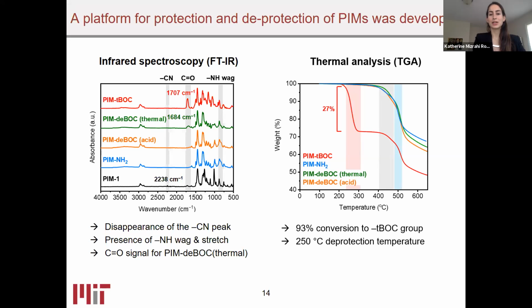In addition, we looked at thermal analysis to evaluate the deprotection temperature for the sample, which is about 250 degrees Celsius, as well as how much we were able to convert into the TBOC-functionalized sample. And it resulted in about 93% conversion, which was very high and high enough for us to see the effects that there could be with deprotection thereafter.